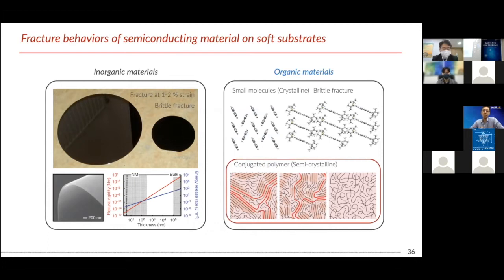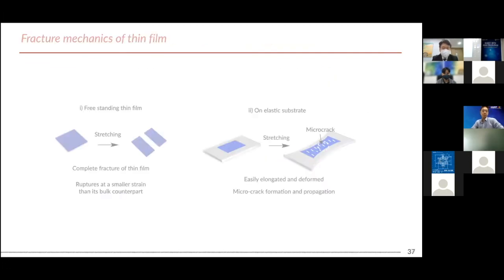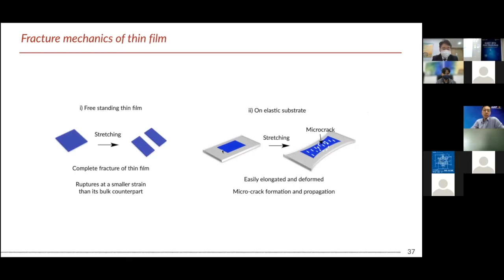So I would like to improve the stretchability of conjugated polymers in a different way. If you look at the fracture mechanics of polymer thin films, we need to consider two situations. One is a freestanding thin film, and the other is a thin film on an elastic substrate. In the case of the freestanding thin film, because of some stress localization effect, they easily form a fracture at a very small strain. But on the elastic substrate, the substrate can retard the stress localization effect. Somehow they can avoid the complete fracture. Instead, they form this kind of micro crack formation.